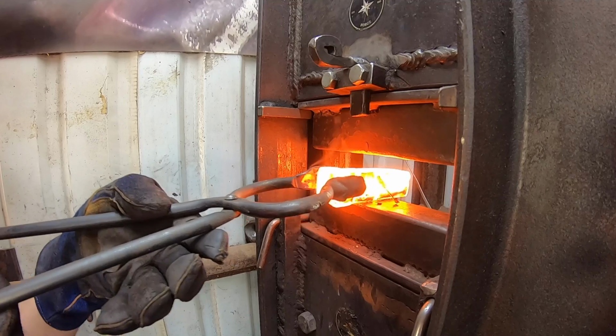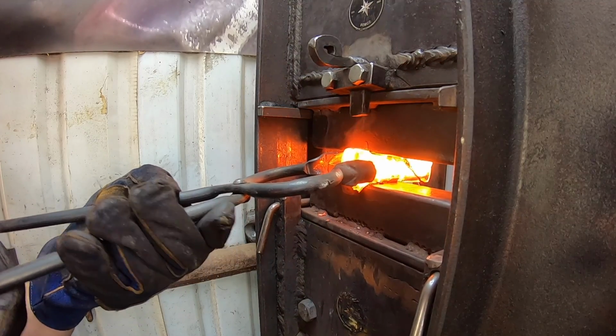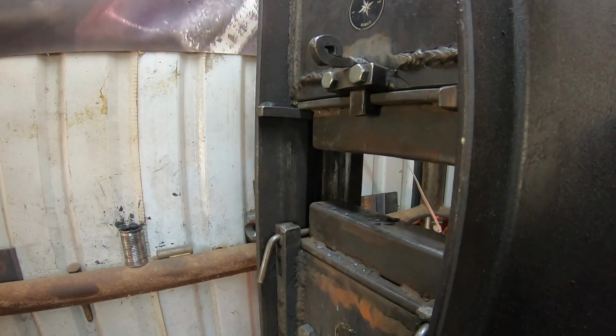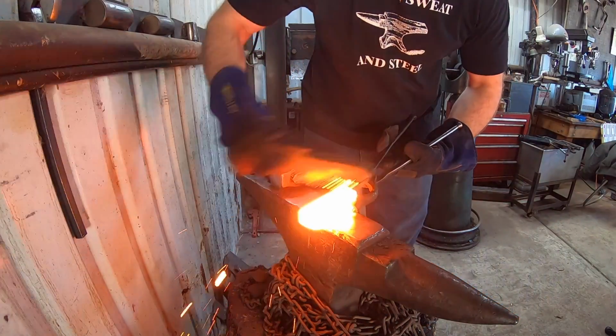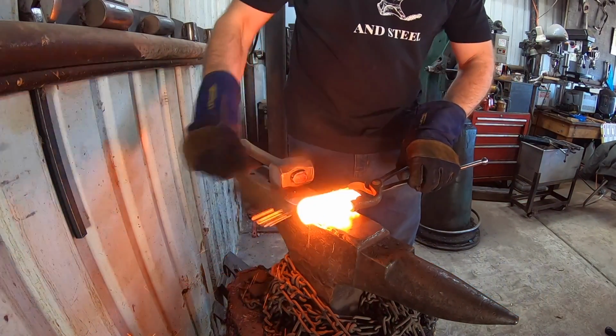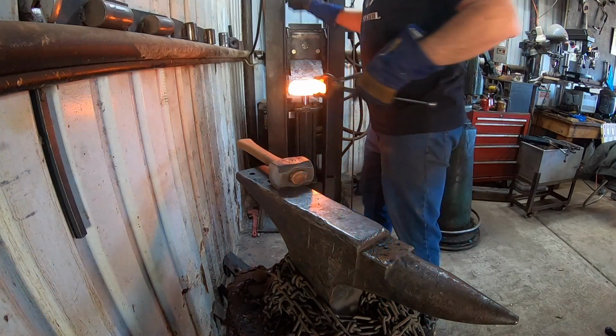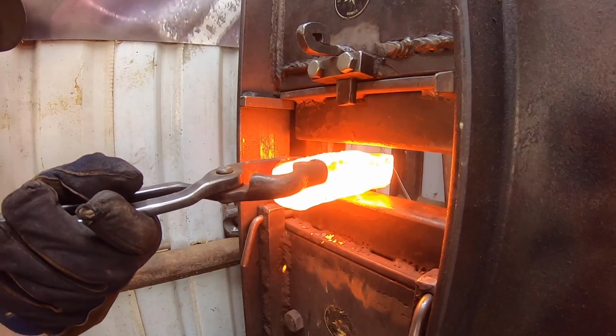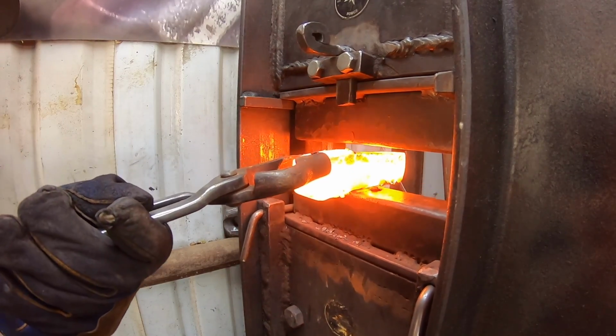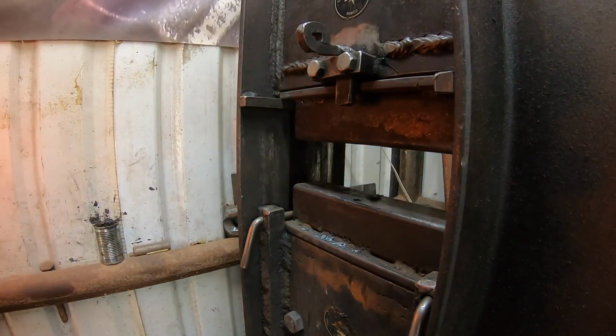I have to be careful to make sure that I forge this in the proper indexing and drop forge there, because as you recall, our blade steel is only on one side of this billet. So if I'm not careful, I could put our roller chain side on the edge, and that would be bad.